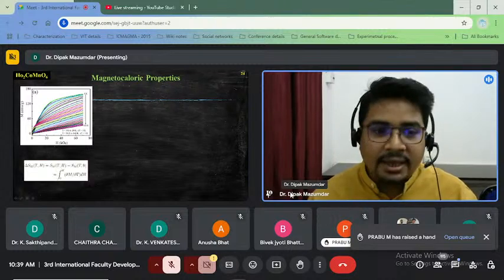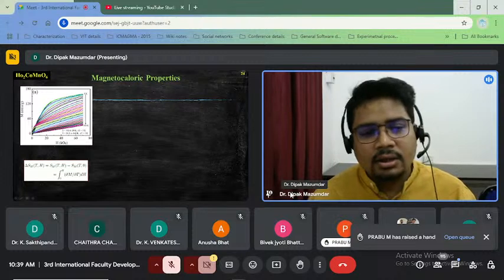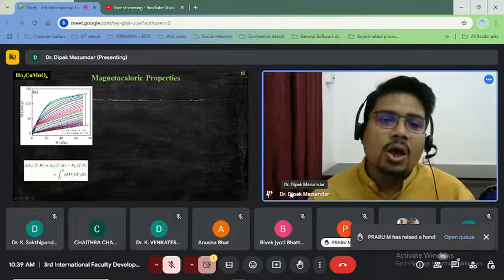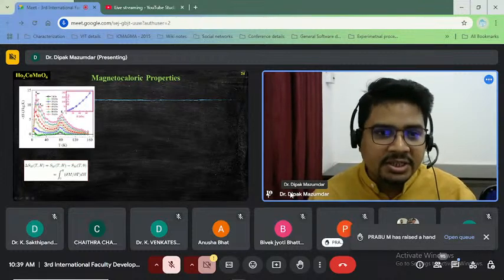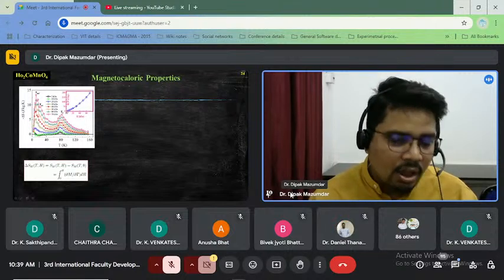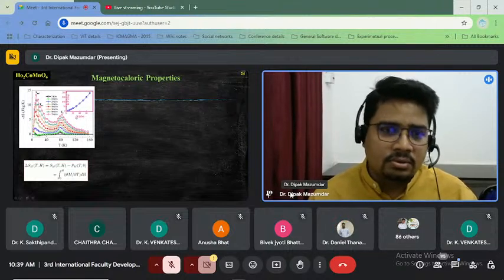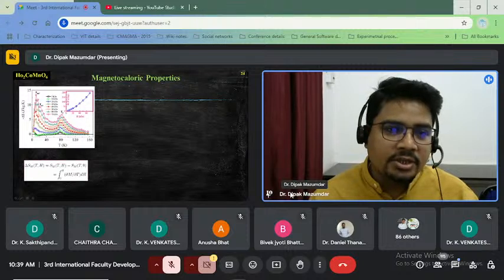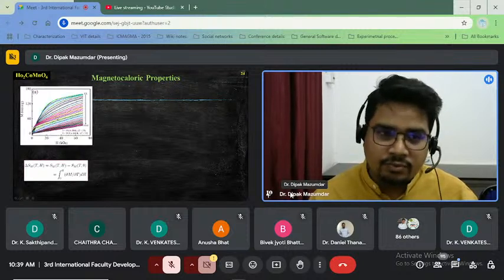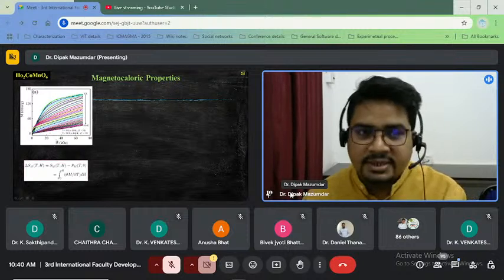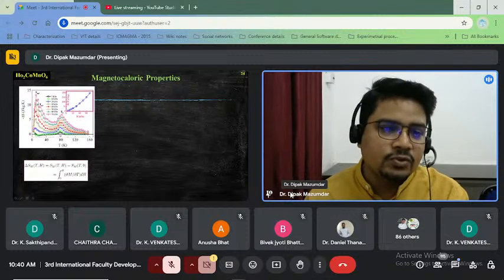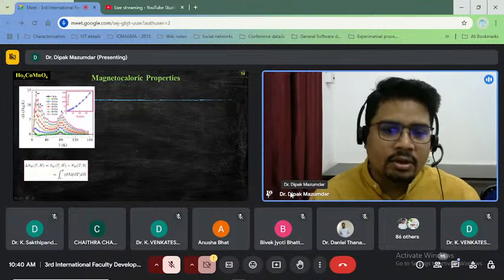And by applying this formula given by the Maxwell thermodynamic relations, we have estimated the magnetic entropy change, and these are the graphs for the magnetic entropy change of this compound. So from this data, we have constructed this graph by using this well-known formula.